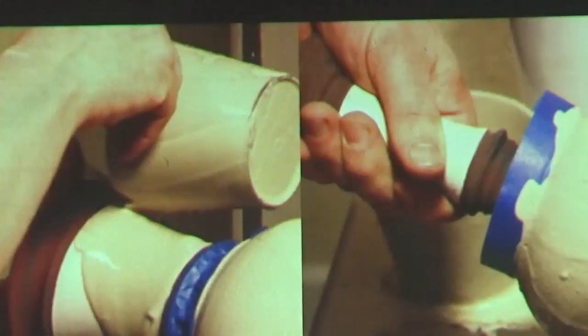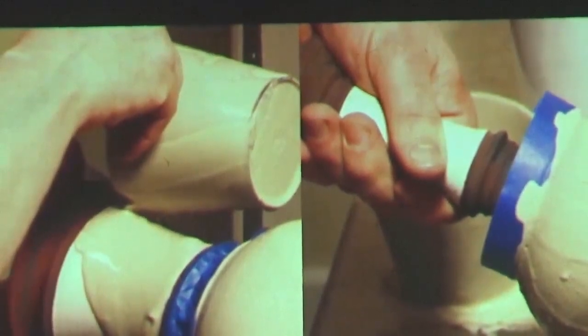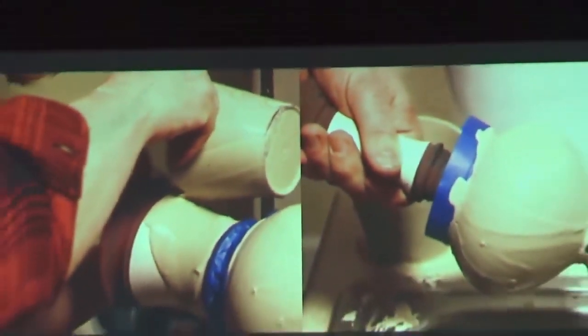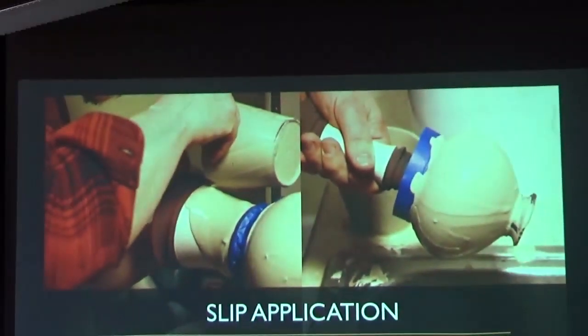So there's a quick picture of applying slip. I choose to pour it. Now, some artists will dip their pieces, but since I do a lot of two-tone work and I want to separate where the cracks are, I choose to pour, and as you can see, mask off a great deal of the piece so that I get these nice crisp lines where the textures change. You can see that there's some differences in thickness. Those will provide different cracking and different looks in the finished piece.